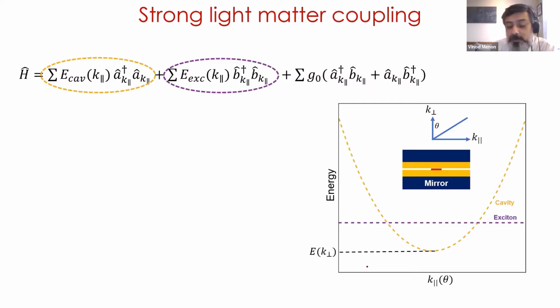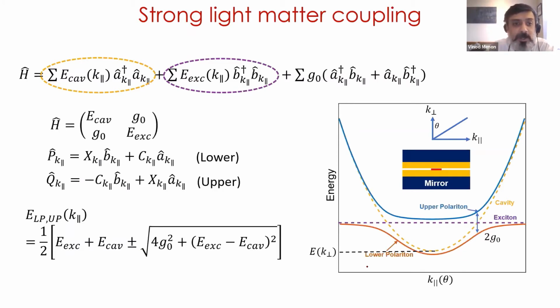You have the cavity dispersion, and now you ask the question, what happens when they get into the strong coupling regime? Here, the Hamiltonian is given by this form, where the off-diagonal terms are the interaction terms, and these are the resonances of the energies of your exciton and your cavity. If you diagonalize this Hamiltonian, you end up getting two new states, depending on the interaction strength, given by the plus-minus terms, one corresponding to the upper polariton, the plus one, and the minus term corresponding to the lower polariton. You can describe these polariton states in a form here, where the terms xk and ck correspond to the fraction of the photon or the exciton in this branch.